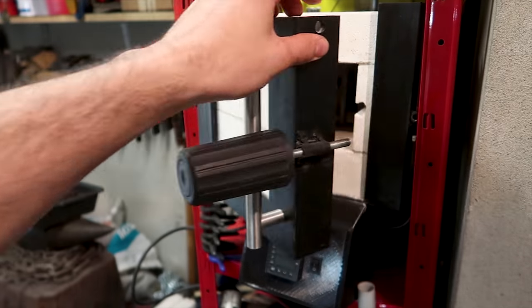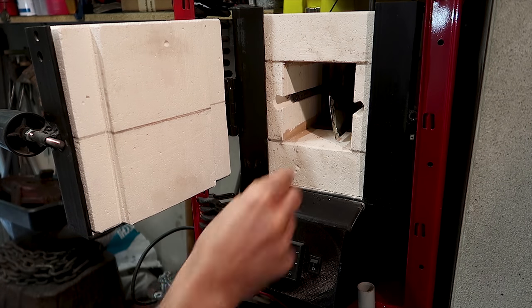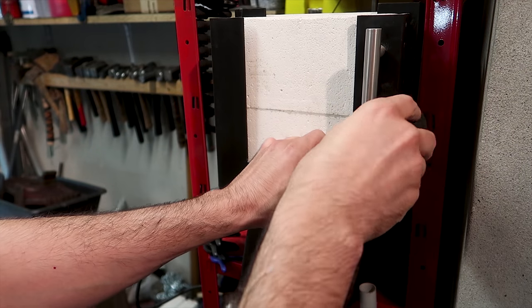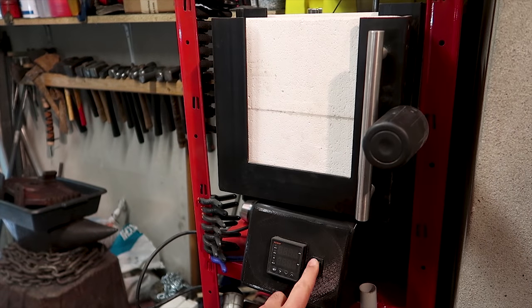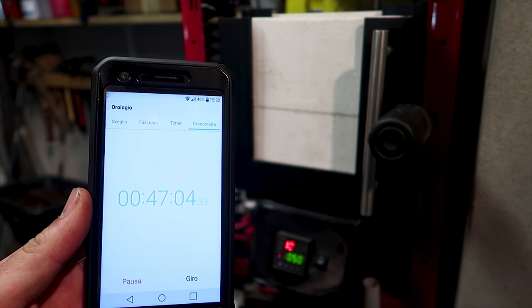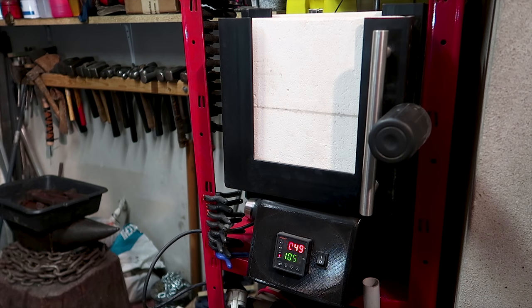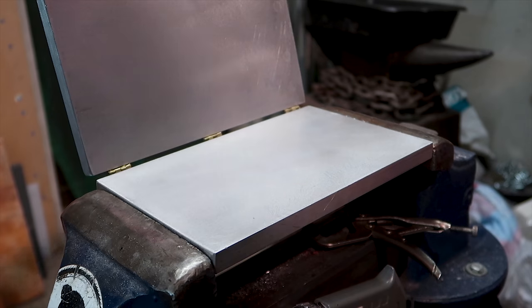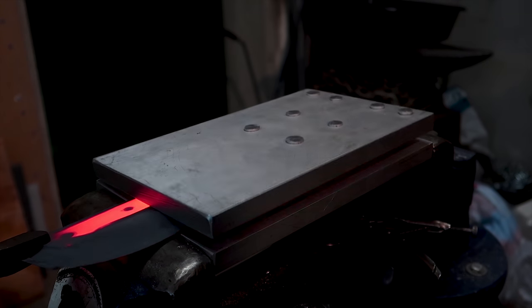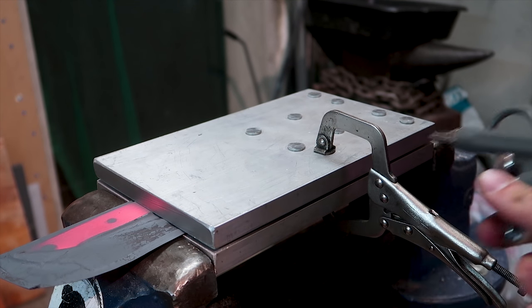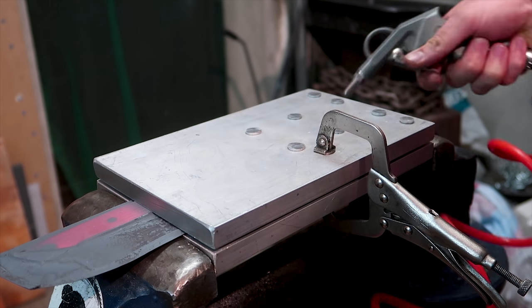With both blades well packed, I can insert them in the oven. I also place in a piece of mild steel that will be used later to heat up the oil. Now the temperature for this steel is 1050 degrees, and it took 47 minutes for my oven to reach this temperature. Then you have to leave the blade at this temperature for 15 minutes. This is why heat treating stainless is pretty much impossible without a temperature controlled oven. After 15 minutes, I take out one blade and I quench in plates. As you can see, I'm using a clamp to lock two plates together, and I'm blowing in compressed air to hopefully make it cool even faster.